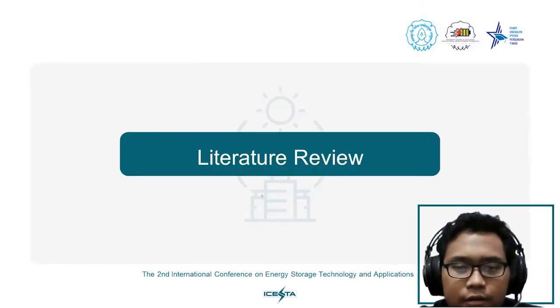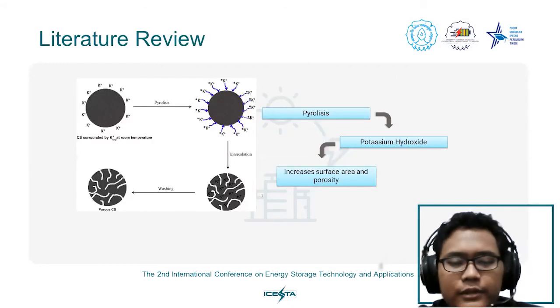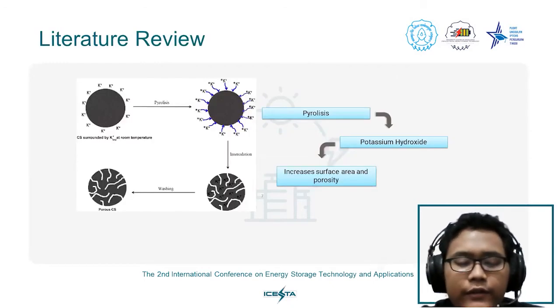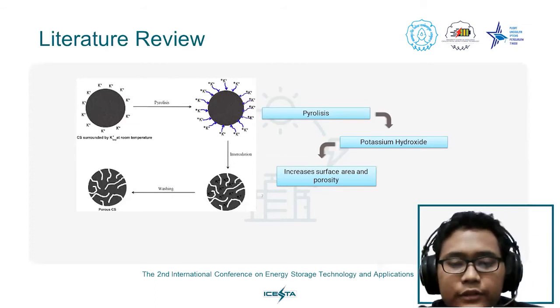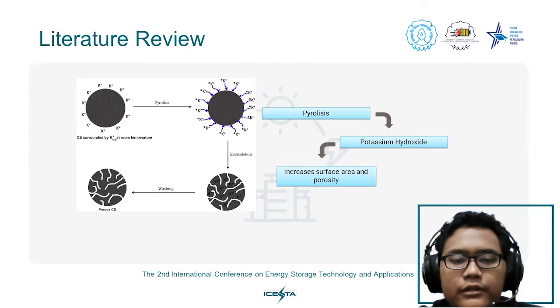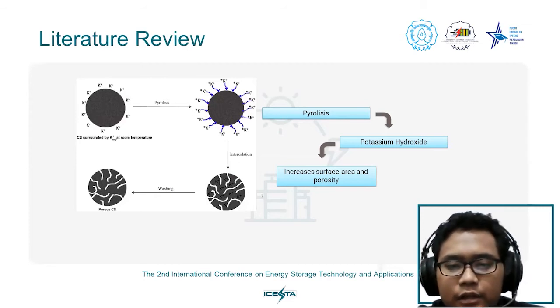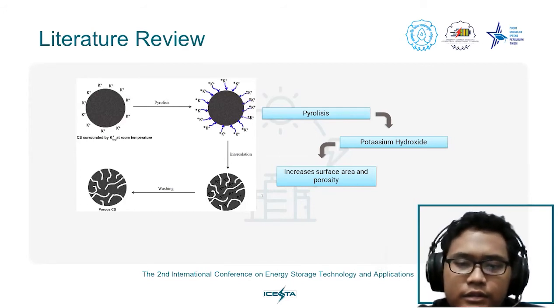Here's the literature review of our paper. The first one is how to get activated carbon, here from the pyrolysis method. The pyrolysis method gives us pyrolysis char. The pyrolysis char is treated with potassium hydroxide to increase its surface area and porosity.